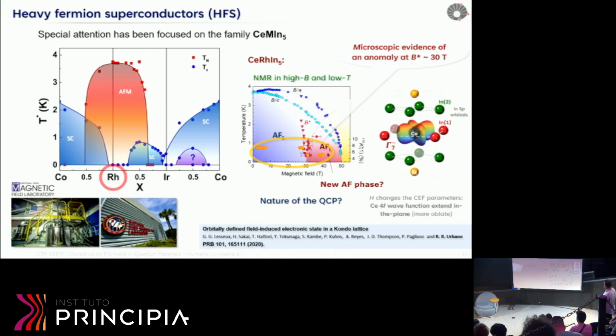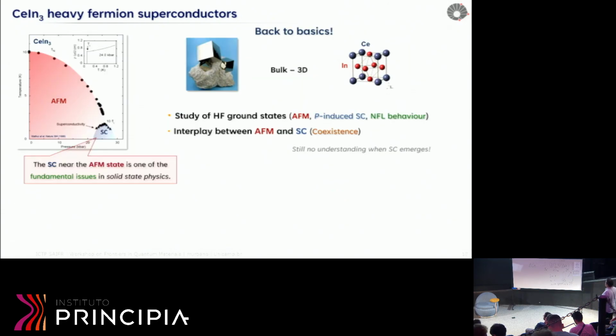And the way we explained this by analyzing the hyperfine field was that the 5/2 contribution to the wave function was getting enhanced, so you get higher, or enhanced, hybridization in plane, and we showed that the Fermi surface was larger over there. But that's not the subject of this talk.